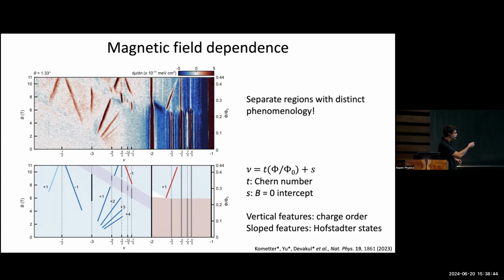And so each of these states you can label by 2 numbers. One of them is the Chern number of the state that is related to the slope that it has. And the other is the zero field intercept S. All of these can be labeled by those 2 numbers. Anything vertical corresponds to a topologically trivial state. So these are like the generalized Wigner crystals, broken symmetry states at integers. Anything diagonal is a topological state. And in this case, these are appearing at high magnetic field. So these are just the Hofstadter states that I was telling you about before. And you can see I've highlighted in different colors different regimes of different behavior that we observe.